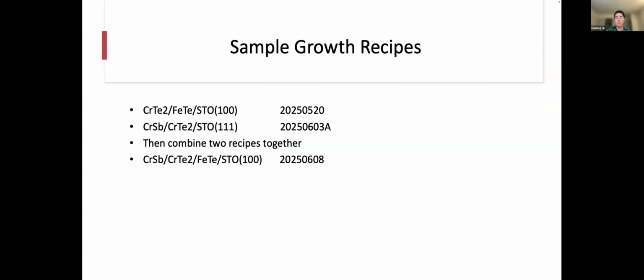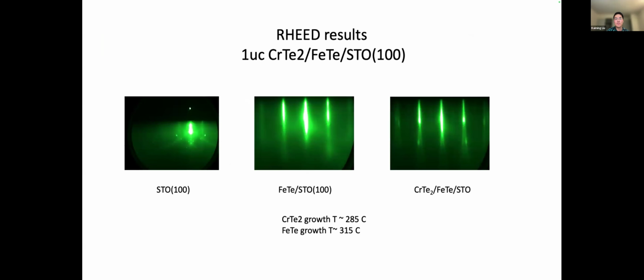From Professor Sarma's group. So we first grow chromium ditelluride on iron telluride on STO100, and then chromium antimony on chromium ditelluride on STO111. And finally, we combine two recipes together. So for the first recipe, these are the RHEED results for chromium ditelluride on iron telluride on STO. So iron telluride gives nice streaks showing smooth growth.